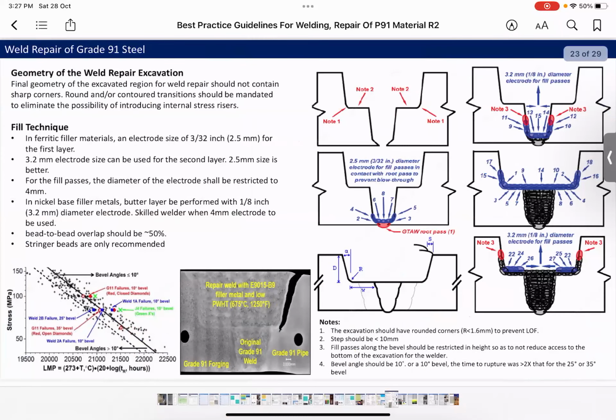For weld repair of grade P91 steel, as I said, this step bevel configuration is recommended not only for weld repair, but also for a new weld as well. So when we have a defect in the weld, this D is the depth of the excavation. We can excavate and ensure that the defect is fully removed by dye penetrant test. And after that, we should ensure that the corners of the bevel are rounded to avoid lack of fusion.